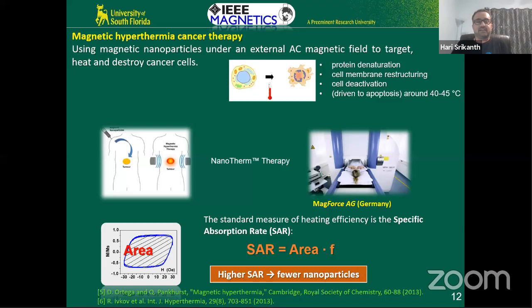Every therapy or every kind of technique that you develop, you need a figure of merit that you need to improve. The figure of merit here is the specific absorption rate, or SAR. And simply put, it's just the area multiplied by the frequency of the AC field that you apply. Now, keep in mind that this is something that is going to be injected inside the human bloodstream, inside the human body. So you don't want to really put in a lot of particles. You need to keep the toxic level low. So we need to come up with strategies to improve the material science of these particles, as well as to come up with ways where we can actually use only a few nanoparticles, a small volume of nanoparticles, and still be able to increase the figure of merit, or the SAR.